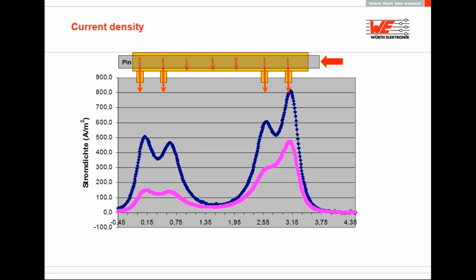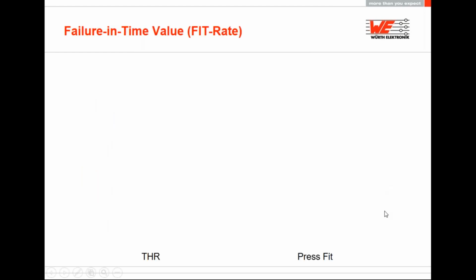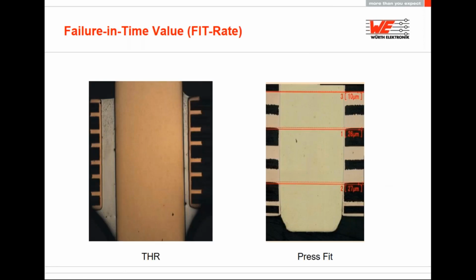And now let's move on to the failure in time value. So the frequency of failure of the press fit parts is decreased compared to the one that is soldered because of the tolerances. If we see on the left the THR, the pin floats and has less resistance on one side than the other. So the current will flow differently than with the press fit technology on the right, where we see a very light deformation of the copper traces, but the contact is symmetrical with all different layers of the PCB.